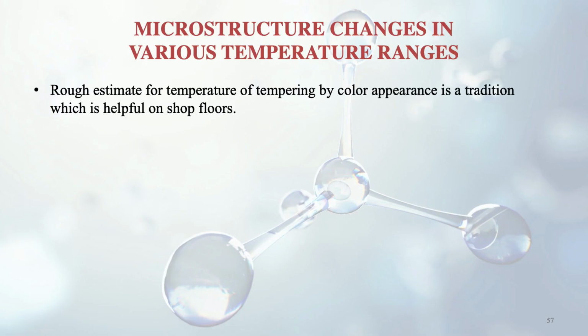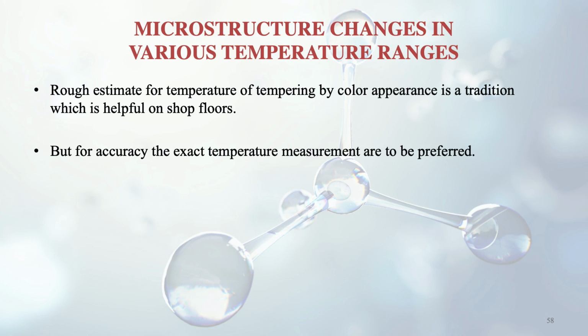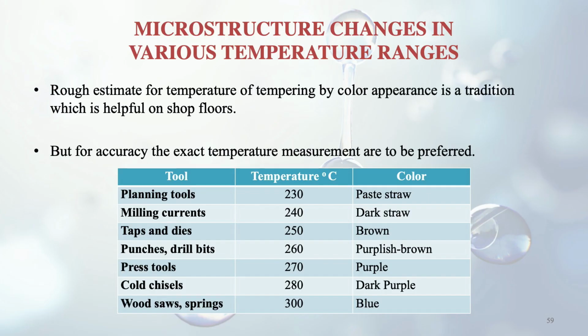A rough estimate of the tempering temperature by color appearance is also a tradition which is helpful on shop floors. It is not that accurate and doesn't give exact temperature measurement, but still just by vision we can get a certain degree of correctness. From the table you can see for planing tools the tempering temperature is 230 degrees and it gives a color of pale straw. Similarly, there are other things mentioned that you can learn from this table, like for cold chisels, the tempering temperature is 280 degrees centigrade and the color is dark purple. There are others also, and it is a kind of guess and not exact, but it still gives a good prediction. Now we will take up changes in mechanical properties with tempering.